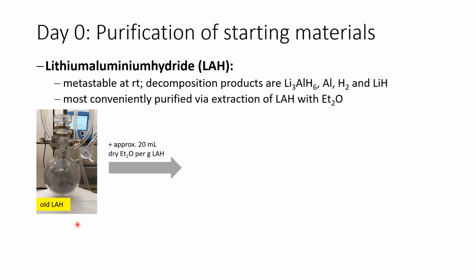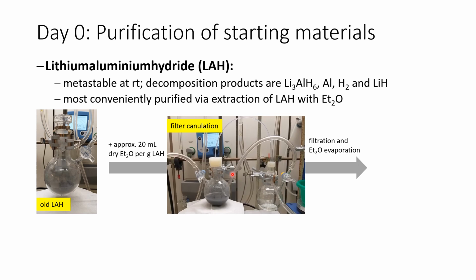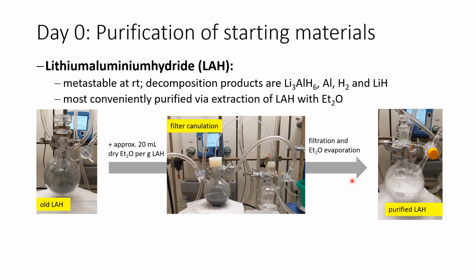To do that, you use your old gray lithium aluminum hydride and put it into a Schlenk flask. Then you add approximately 20 milliliters of dry diethyl ether. You should let this mixture stir for a few minutes and then do a filter cannulation. After the filtration and the evaporation of the diethyl ether, you should get a nicely colorless and very clean purified lithium aluminum hydride. This can be easily used for the reaction.